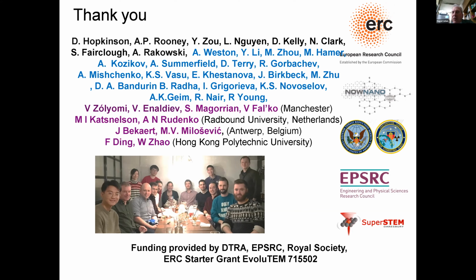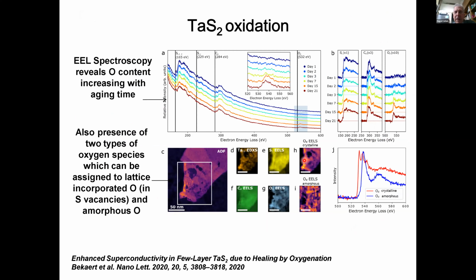You have in the oxygen onset, in the oxygen edge, the plasmon loss is very different for the 2 different spectra. Does that say anything on the? Can you show it, maybe one before the last? Yeah, let me try and go back in the slides. Okay, here. Yeah, on the bottom right. So you see quite a different plasmon loss, I would say.